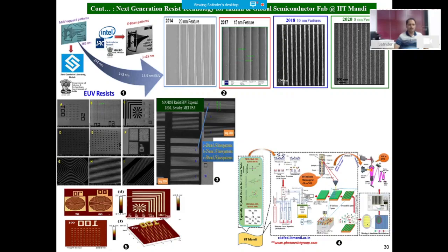Ultimately this is going to be accepted, or scaled up, by the industry, and this material should be sensitive to EUV, extreme ultraviolet lithography, 13.5 nanometer. So this material was developed by us, and then we patterned it with EUV at Lawrence Berkeley, and these are our results on top of that.